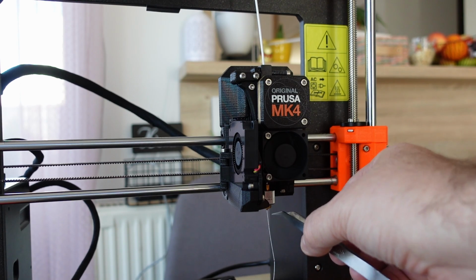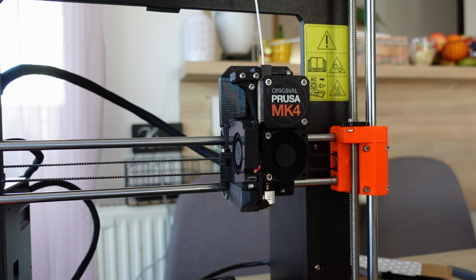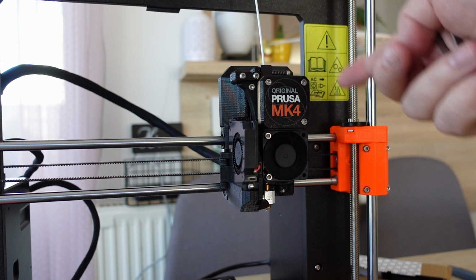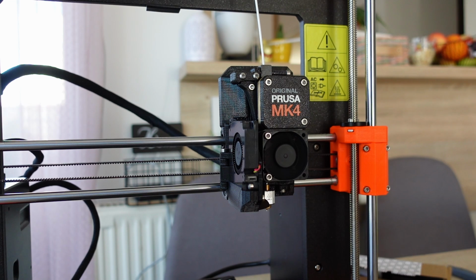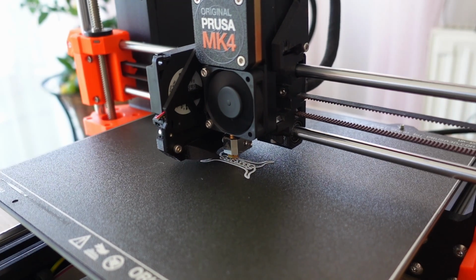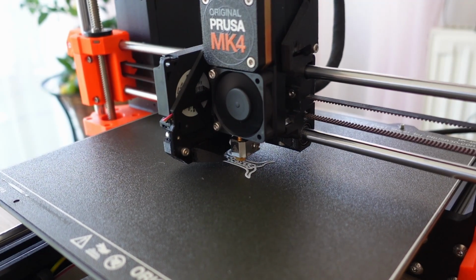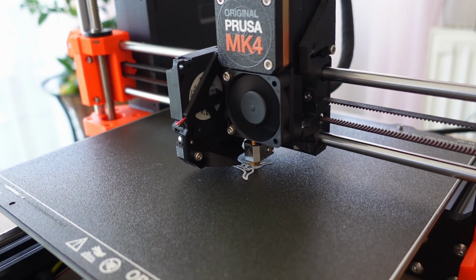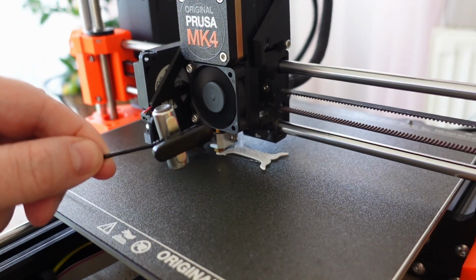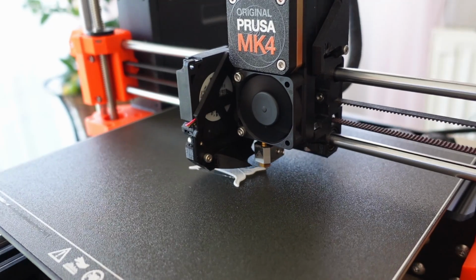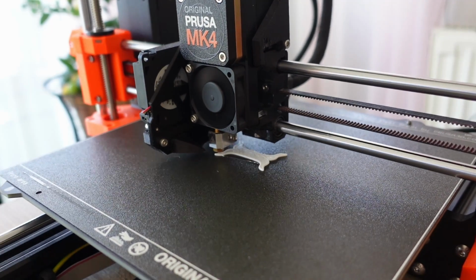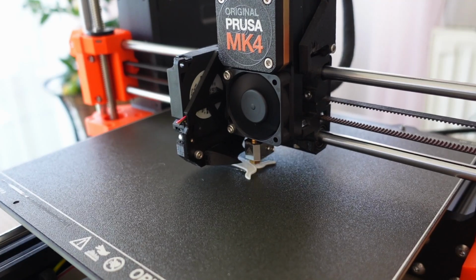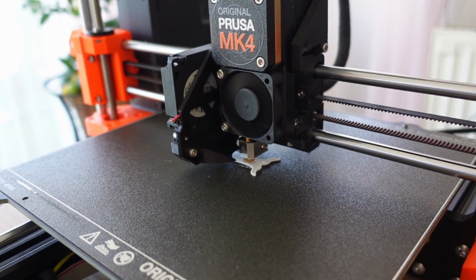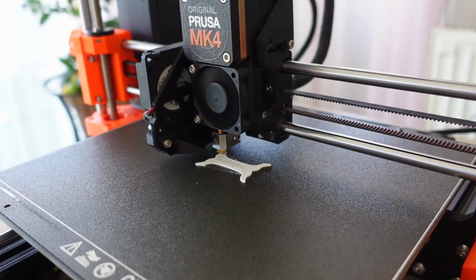And it's extruding on the other side, so no problems with this hardened version, but I could hear some small micro cracks, so I believe that in this 1 year it absorbed some moisture. We will see, maybe I have to dry this too. The start is great, there is just a little bit more stringing, but the first layer lays down perfectly. Definitely I can recognize those micro cracks, so this filament has some moisture in it, and we will see after this temperature tower if it needs some drying or not.